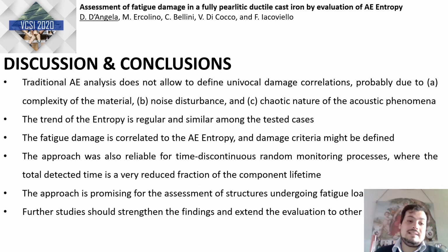We found that the fatigue damage is correlated to the acoustic entropy, and the damage criteria might be defined accordingly. We also applied this approach as a pilot study, a study on time discontinuous random monitoring processes, in which the detection windows were very reduced. So the monitored life of the structure was very, very small compared to the lifetime of the structure.